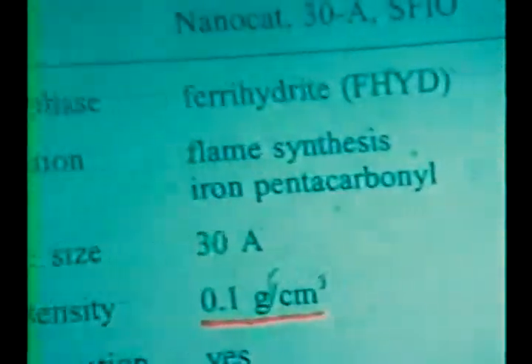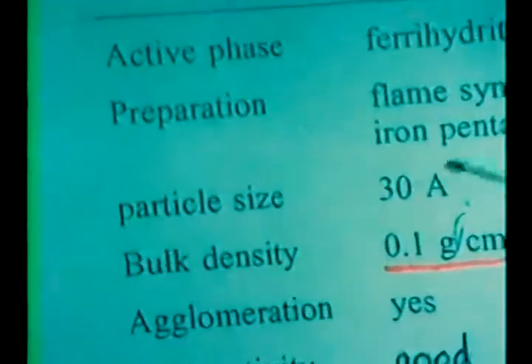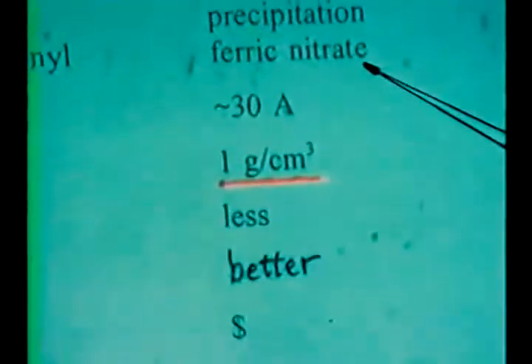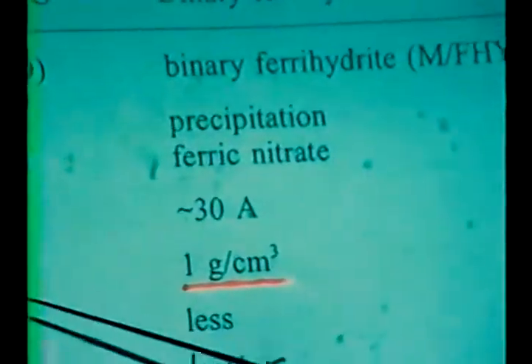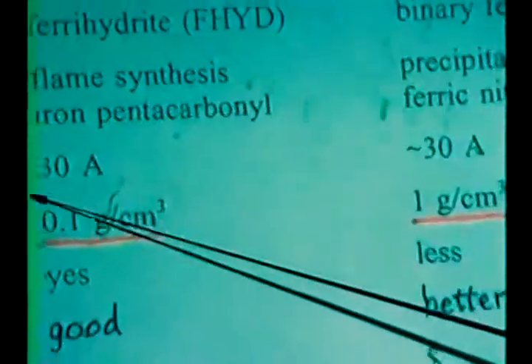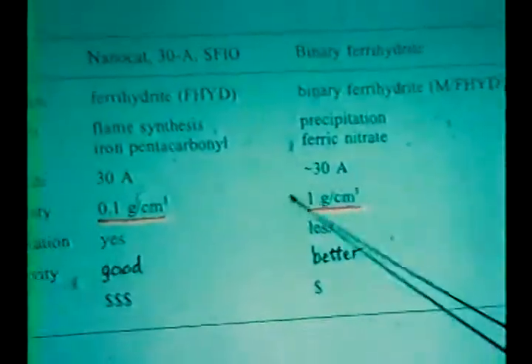The active phase for the 30 angstrom catalyst is ferrihydrite, and we also have binary ferrihydrite. They use flame synthesis; we use iron pentacarbonyl, and we use precipitation with ferric nitrate. The particle sizes are about the same. Bulk density is the only difference.